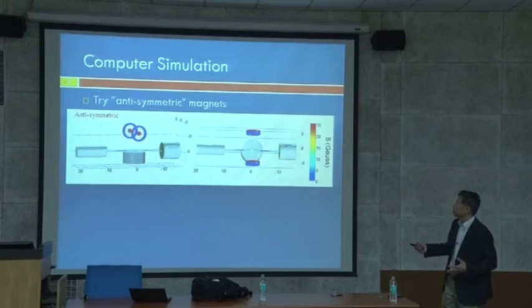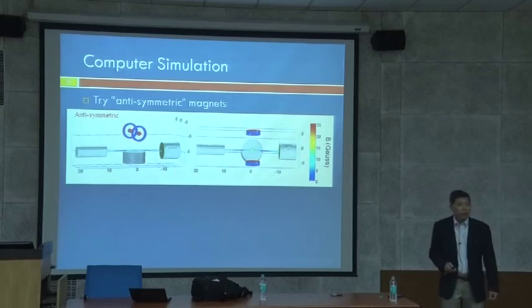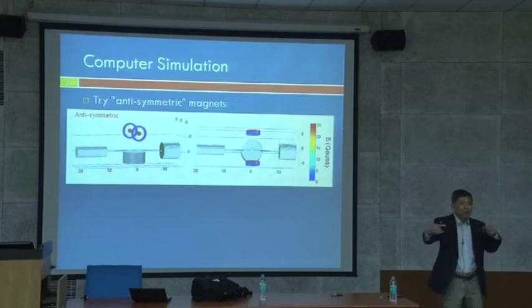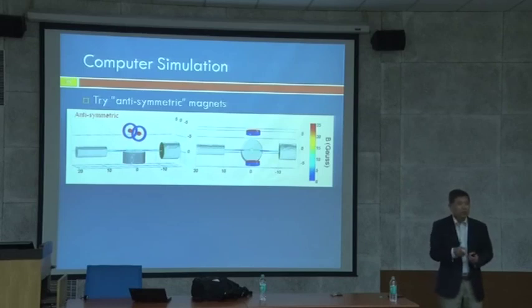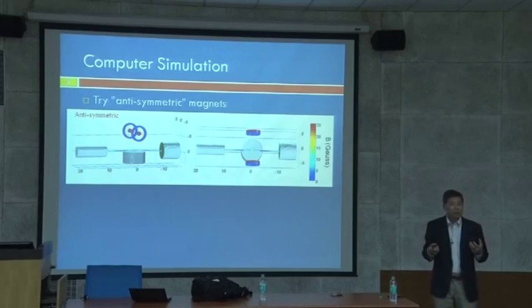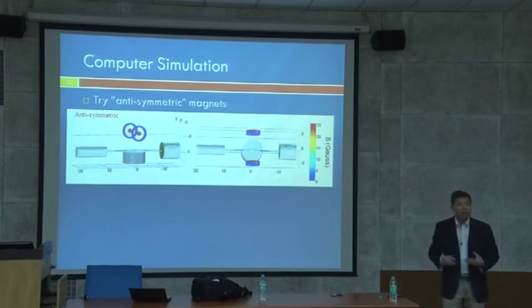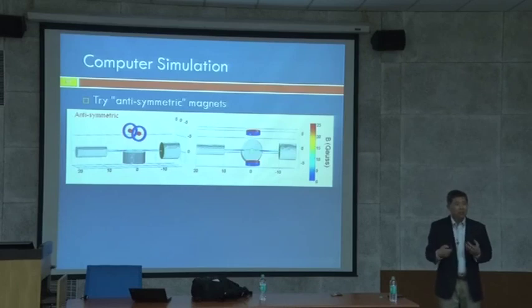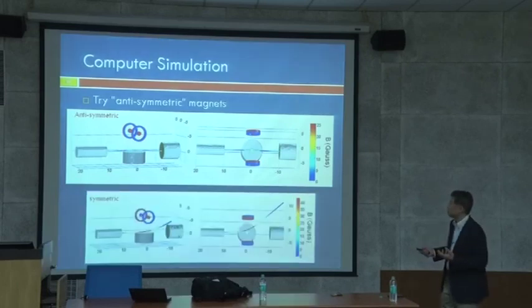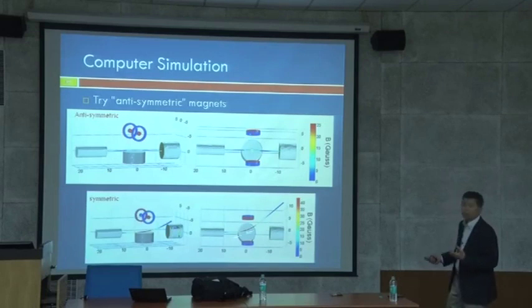And you can actually see that the beam is straight, and this is all the simulation of it, so you can have a nice RHEED pattern. We built this chamber in our lab, using two sputter guns with the RHEED gun, and when you set it up and hit the phosphor screen, initially we couldn't see it. Now, after doing this, the beam is at the center of the phosphor screen. So I think this is not very difficult. You can adapt this and grow at high pressure with in-situ RHEED and multilayers. It's a very nice technique. The symmetric one, by comparison, has a very serious bending problem.